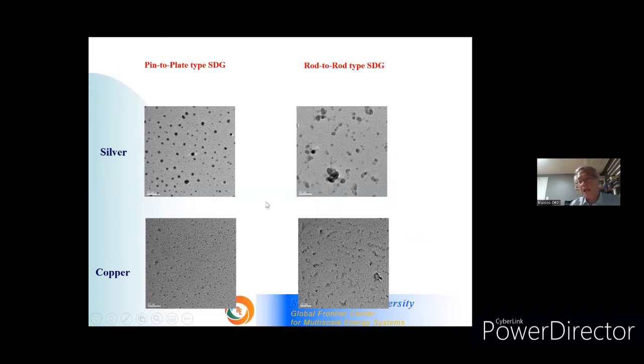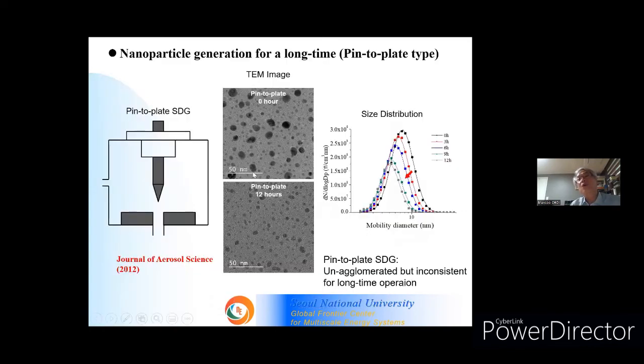However, we found some problems with our pin-to-plate spark discharge chamber. Although this pin-to-plate type generates unagglomerated nanoparticles, very very small particles, we found that the size distribution changes after long time operation. Initially at 0 hours, but at 12 hours we are generating much smaller particles. This inconsistency over long operation is due to erosion of the tip and plate.